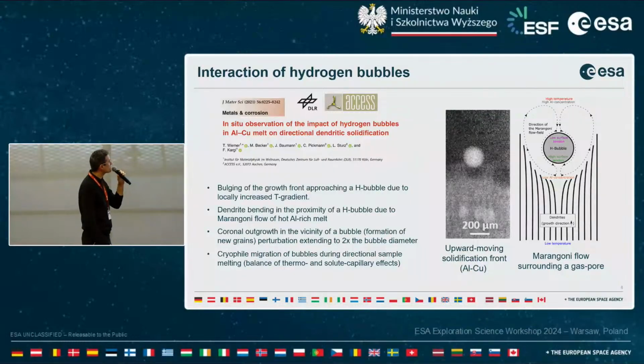Another effect would be a dendrite bending in the proximity of the bubble due to Marangoni flow occurring around the bubble. This Marangoni flow has other impact. It can induce so-called coronal outgrowth in the vicinity of the bubble, inducing, for instance, the formation of new grains or misoriented grains. And this perturbation can extend up to twice the diameter of the bubble. So the impact of the bubble is very significant.